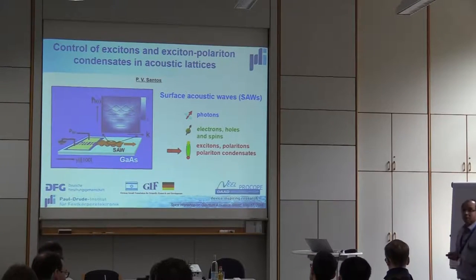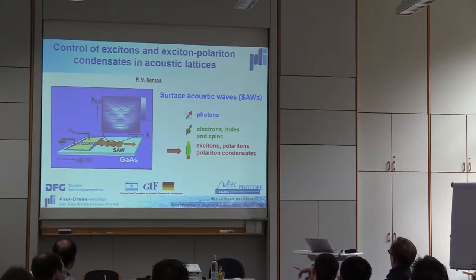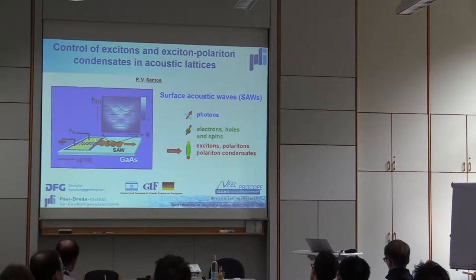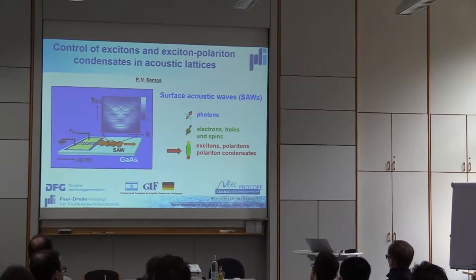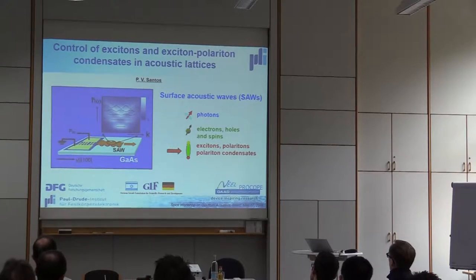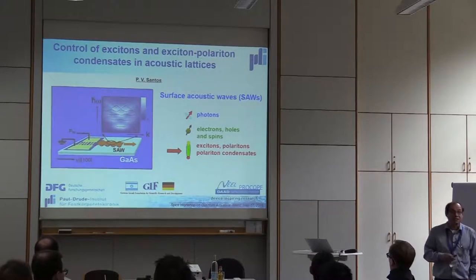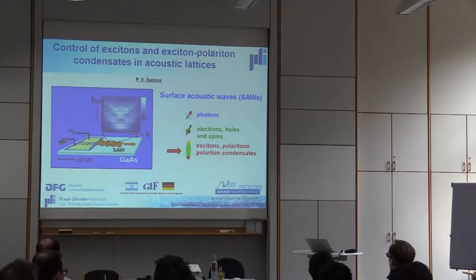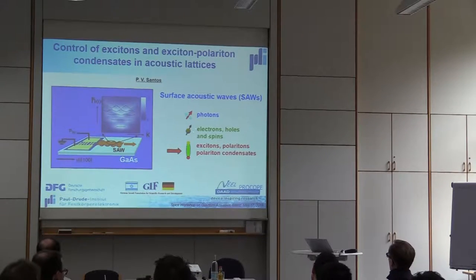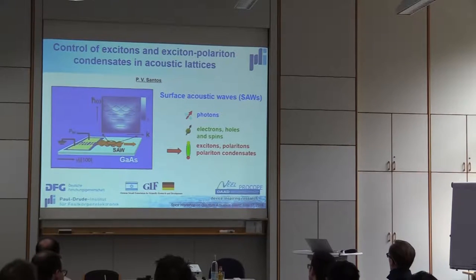One of the main topics of the workshop is surface acoustic waves. Surface acoustic waves are vibrations propagating along a surface, and one of the nice things about these vibrations is that they can be relatively easily produced using these kinds of structures and interdigital transducers. They propagate in semiconductors and other materials, and we have been interested in using these vibrations to control excitations in semiconductors. They are very nice for controlling photons and can also be used to control and transport electrons, holes, and spins.